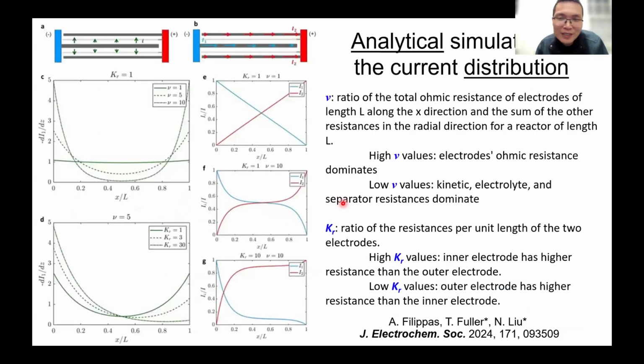configuration and geometry. And we did some simulation to figure out the different scenario, like conductivity of the electrode is important for this device to be very long, because the electron has to deliver this way, right? It's different from the planar configuration. And also the conductivity of the two electrodes has to be symmetric. If one is more conductive than the other, then the reaction will concentrate on one side.